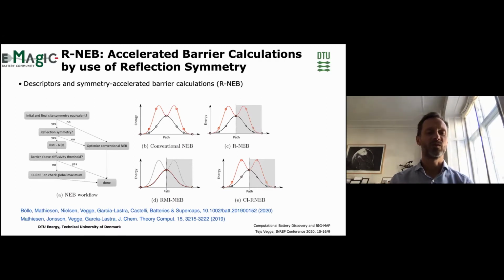So this is work done by Nicolai Mathisen and Juan Maria Garcia Lastra, trying to only use the minimum requirement in terms of assessing the kinetic properties. So if the system has reflection symmetry, we simply calculate the energy of the magnesium when it is at the mirror plane. If that is above a certain threshold, we know that that is the lower bound for magnesium diffusion. If that is too high, we discard the material.